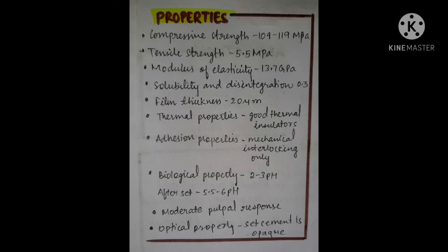Then next is the properties. The first is the compressive strength, which is very high, 104 to 119 megapascal. Then tensile strength, which is 5.5 megapascal. Then modulus of elasticity, which is 13.7 gigapascal. Then solubility and disintegration, which is 0.3. Then film thickness, which is 20 micrometer. Then thermal property, good thermal insulator. In adhesive property, there is only mechanical interlocking.